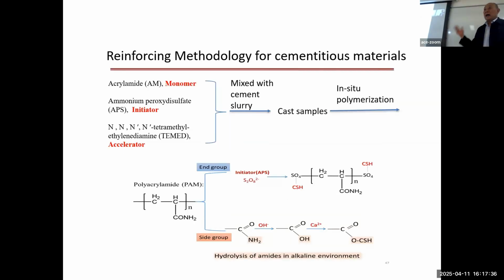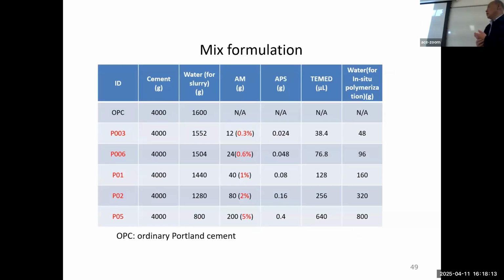Now on the other side, we use nanoparticles to reinforce the hydrogel. Now we can use that to reinforce our cement-based material. So we did the same thing. We put in the monomer, initiator, and accelerator, and we mix with the cement slurry and cast samples. During the hydration, we expect an in situ polymerization to happen, and then it can form a second network in the cement-based material. So this is one of my students' PhD thesis.